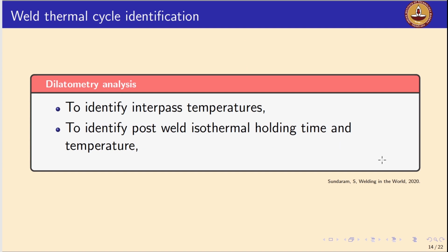So the weld thermal cycle here means identifying the interpass temperature, the temperature at which the second pass is deposited on the first pass. The interpass temperature is one of the important parameters because it lets the first pass weld transform at isothermal bainitic temperatures. So upon maintaining the interpass temperatures, once the welding is carried out, we also have to maintain the entire weld at an isothermal holding temperature so that the weld can transform into a completely carbide-free bainite microstructure.